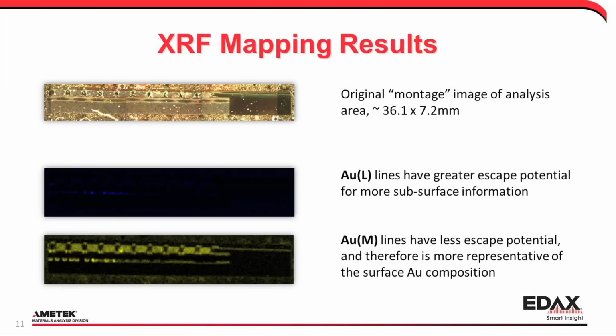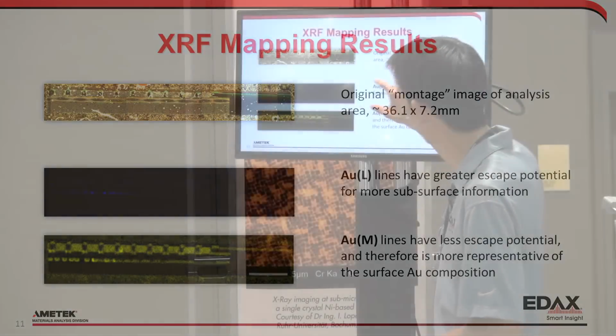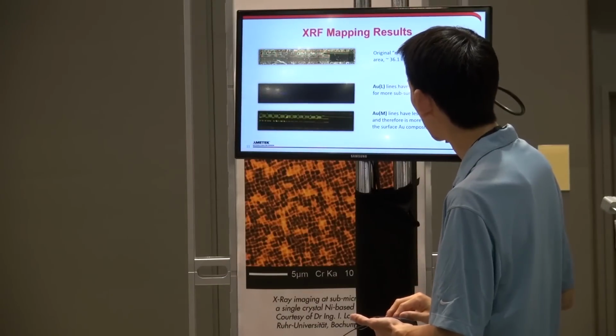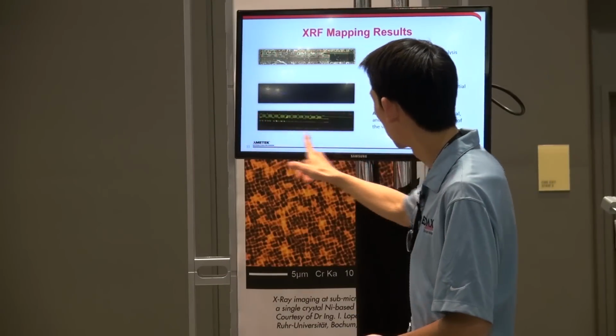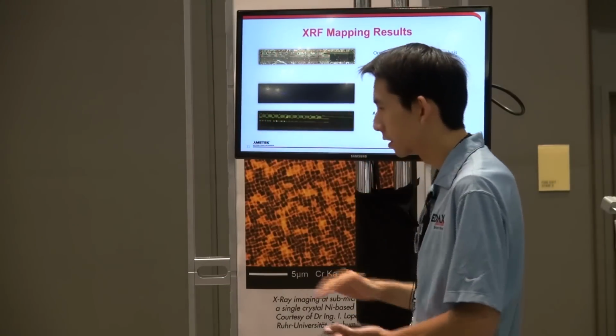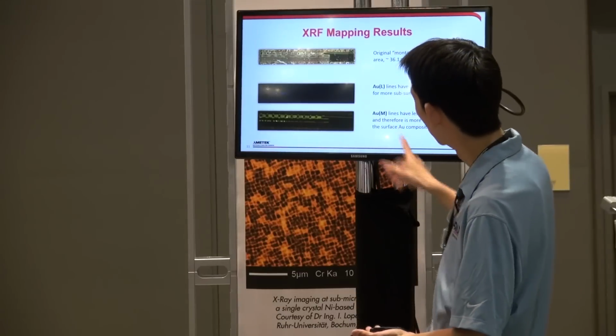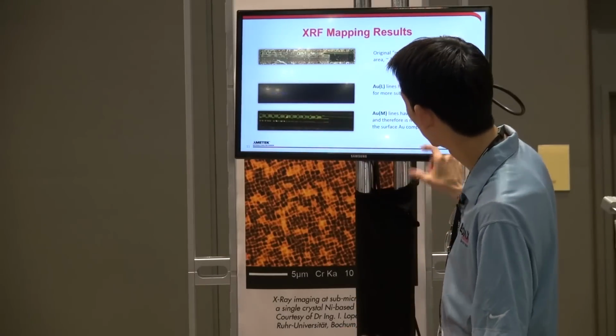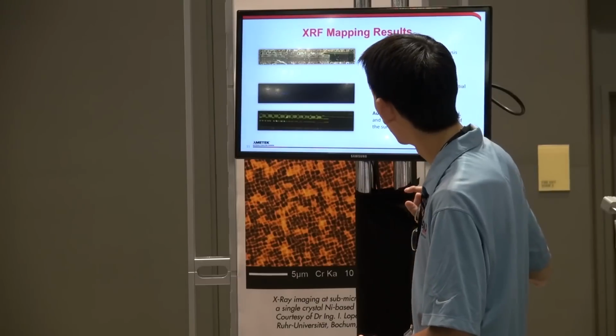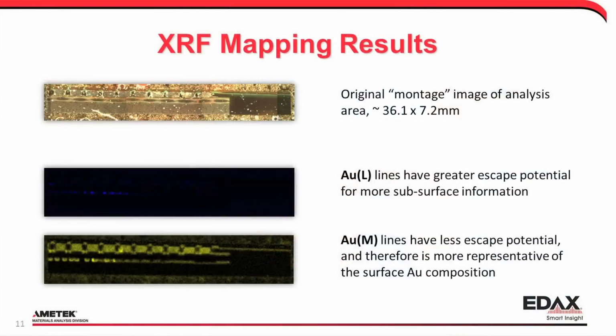And as we were saying before, they both have different escape potentials, and so you get different information from getting to use both lines. The gold L line would probably be too high for EDS, and normally you probably get the M line, which is more representative of the surface. Whereas the L line here, although it's blue and not the greatest color, comes from a greater depth underneath the surface, and therefore you see what's more representative of subsurface presence of gold.